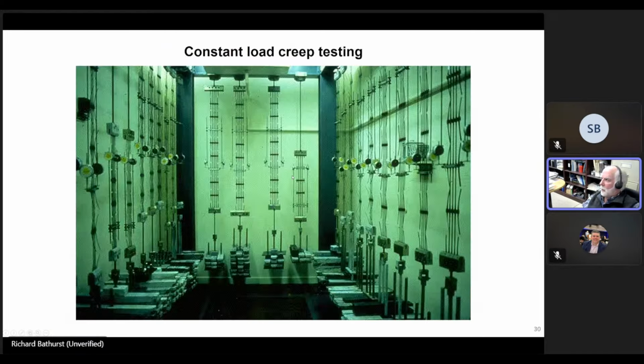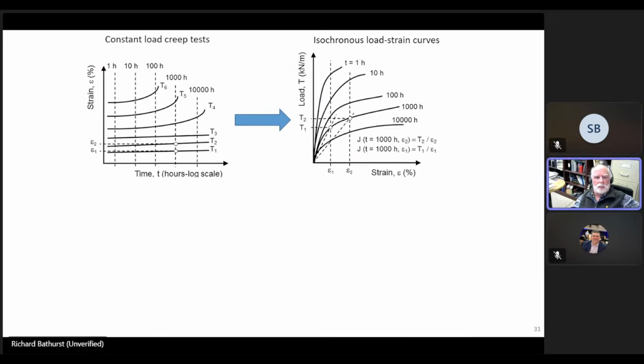So the question is, how can I develop a model that handles this rate dependent nature that I've just spoken about? Well, the best approach is to gather data from constant load creep tests. And from these constant load creep tests, which are shown on the left here, strain increases with time, and load. And from those constant load creep tests, we can generate a set of isochronous load strain curves, load versus